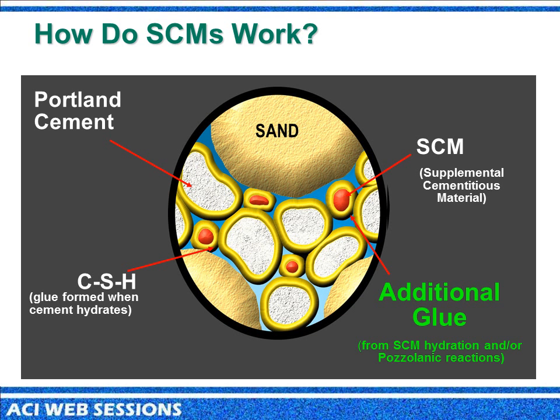More importantly, what you'll see in the data we're presenting is the synergistic opportunities that happen when we use slag cement in the ternary blend. As slag cement continues to hydrate over time, we can really impact the permeability of the concrete mixture. We certainly get a nice kick from silica fume up front, but when we look at the long-term effects and the long-term durability, we're really obtaining those by using slag cement in the ternary blend.